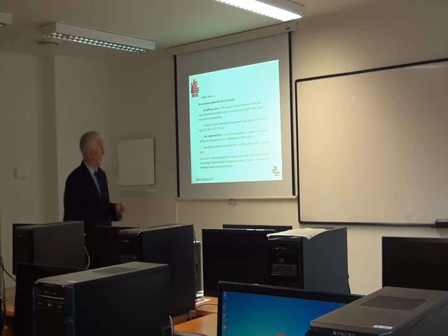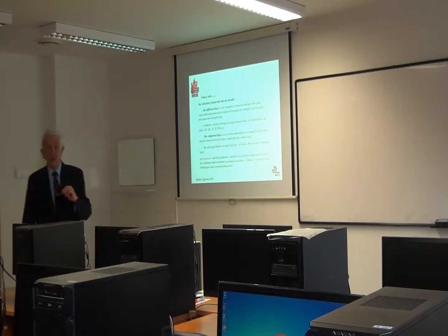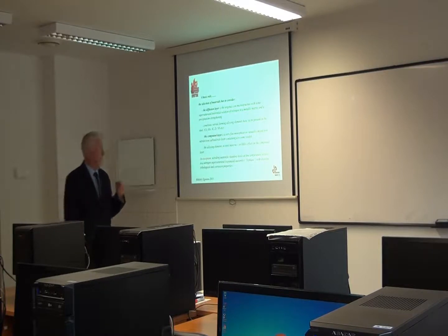And this is extremely important. In this case, the alloying elements don't play a role. The alloying elements are only important because there has to be a support layer. The surface of the compound layer has to be supported by a relatively strong diffusion layer. That's the only role of the alloying elements. In the compound layer, they don't play any role.